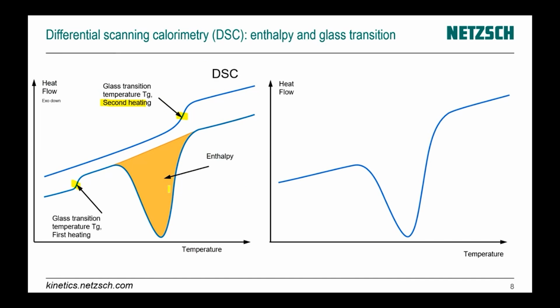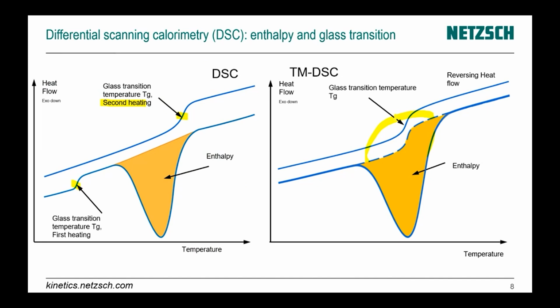Sometimes we have something like this, where we have a glass transition somewhere inside the range of our curing. And usually if we have only one DSC curve, then it is impossible to find where the glass transition is. In this case, we use another technique, which is temperature modulated DSC. With temperature modulated DSC, we can find a reversing heat flow, which shows how our heat capacity changes with the temperature. We can use this reversing heat flow as a baseline here. After that, we can find the enthalpy very well, and we can find the glass transition temperature for this case.